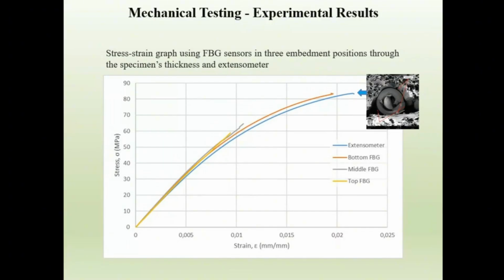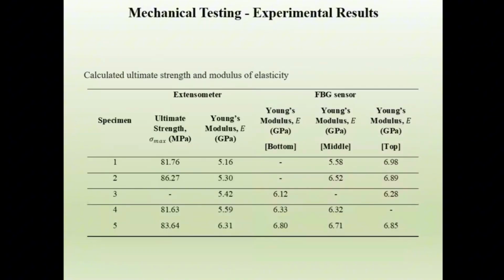So the results were very interesting, and actually they show that the general mechanical response of the material, for that type of composite where we have the short fibers along the applied load, the in situ mechanical response is pretty good and is very close to the one that we get out of an extensometer. So to go very quickly, those are some numbers that we get for the Young's modulus out of the extensometer and the fiber optic sensors.